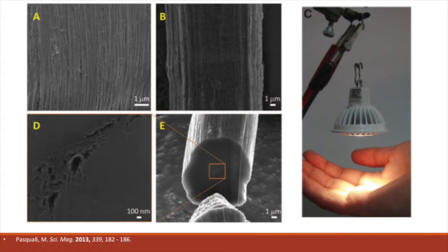In 2013, Matteo Pasquali and researchers at Rice University took the carbon nanotube sheet a step further and successfully spun carbon nanotubes into multifunctional nanotube fibers out of nanotube forests. These fibers exhibited elongation up to 1.5% of their original length before snapping, a tensile strength of up to 1.3 gigapascals, and a high conductivity of 2.9 megasiemens per meter.